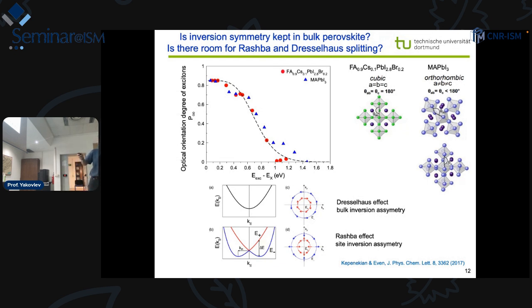At least what we made here in this experiment, we compare these FAPI materials, which is about cubic, with the MAPI material, which is orthorhombic and strongly anisotropic at low temperatures. And we find out that the optical orientation detuning here is exactly the same. So we may claim that at least for the bulk perovskite, we have also examined two other materials I didn't show here, the inversion symmetry is not lost, and Rashba and Dresselhaus splittings are not in the game. For two-dimensional or for the surface, it of course may come.